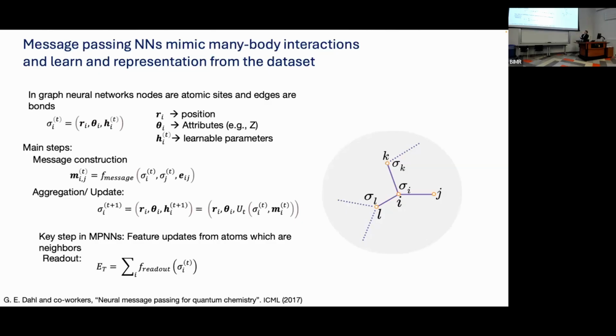We then construct a message between different sites. So this simulates a two-body interaction where you have site i and site j, and then you have some edge function e_ij that defines the interaction between the two, and then you have some message function that aggregates that information. And at each step, you update these parameters, h_i, with information that's aggregated from its neighbors. And that's this aggregation update.